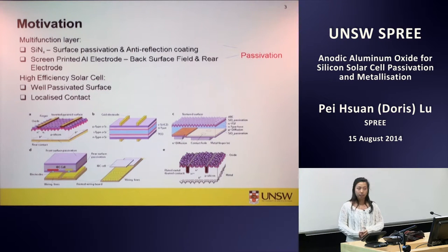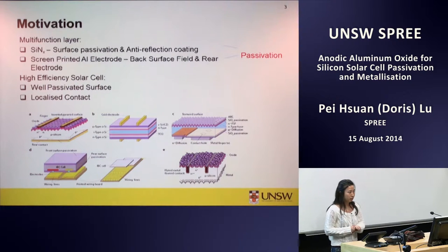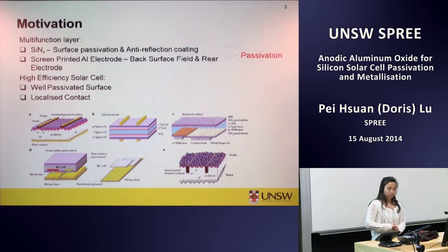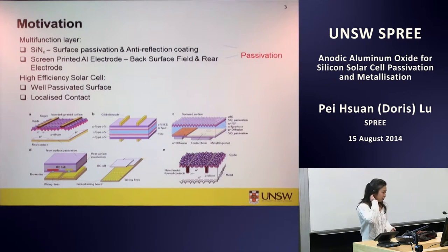So why do we need to find an alternative material for rear surface design? Silicon nitride and screen printing aluminum electrode were quickly adopted into industry after they were first developed. And it's interesting that despite lots of new innovative ways to do the front surface and rear surface, silicon nitride and screen printing aluminum electrode still dominate more than 96% of the market share. They both do surface passivation and another function, which I will call a multifunction layer. For example, silicon nitride can provide surface passivation and act as an anti-reflection coating. And the rear screen printing aluminum electrode, after firing, can provide a back surface field and at the same time act as the rear electrode. They have one thing in common, they both provide passivation.